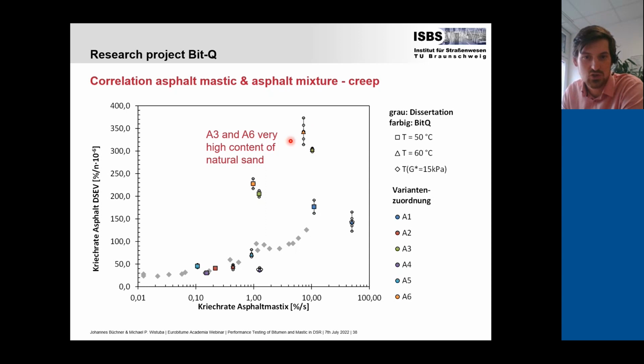However, there were 2 mixture types and 2 mastic types, correspondingly the number 3 and the number 6, which did not follow our expected trend and were kind of confusing for us in the beginning. But when we analyzed the composition of each material and each mixture, we identified that these 2 materials had a very high content of natural sand in the mixture. And of course, we cannot include or see the effect of sand in the mastic, because mastic only includes the filler, the very small particles. And if there are larger particles which are round, so to say, they influence the creep behavior of the mixture more than they influence the creep behavior on the mastic level.